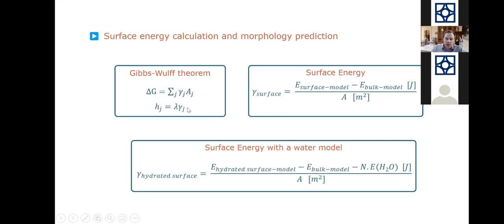Now we introduce also a parameter here that helps us, in fact, to fit a little bit the results, because as we will see, crystal structures are not only determined by thermodynamics, but also by kinetics. And in order to have an idea on how important is the kinetics in the structure, we can introduce this relationship where we, in fact, multiply our surface energy with a parameter lambda and introduce this. And so we can then, in fact, evaluate how important is the kinetic part in our system, in our morphology.